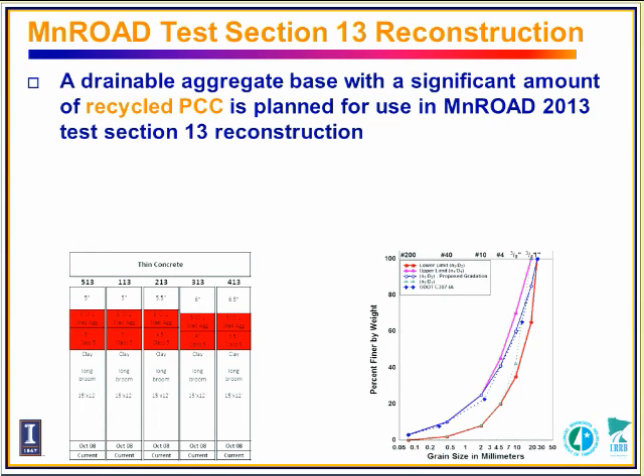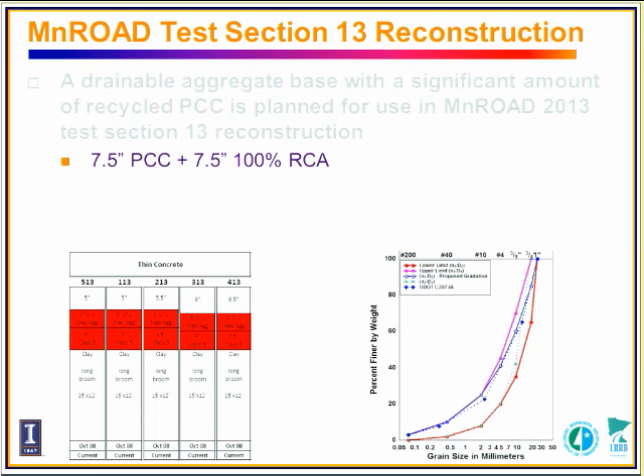Here is an application of this method. MnROAD test section 13 is under reconstruction, so they requested an unbound aggregate base for this recycled PCC pavement. This pavement structure is 7.5 inch PCC and 7.5 inch 100% RCA. For this material, it is required to have better shear strength behavior and locking behavior, as well as to maintain durability. So using this framework, we came up with a gradation and sent it back to them, and hopefully we can get some instrumentation data and feedback from the real construction. Then we can further validate and redefine this framework.